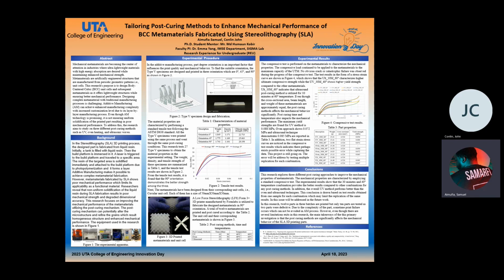In this research, 12 parts in three batches were printed, but only 10 parts were tested, as two parts were defective. Due to the complexity of the part, print failures sometimes occur, which may not be avoided in the AM process. However, even though there are several limitations in this research, the main takeaway of the primary investigation is that post-curing methods significantly affect the mechanical behavior of SLA 3D printing. Thank you.